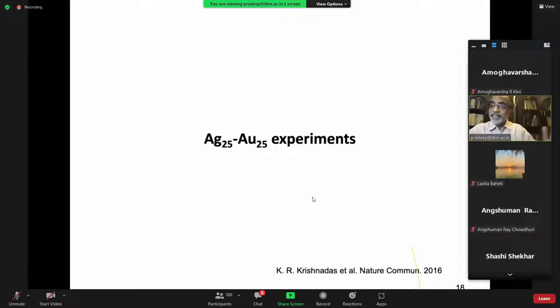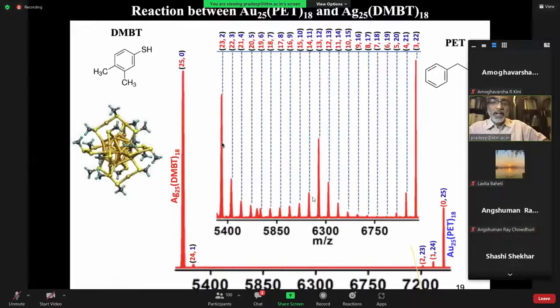Then immediately we started looking at another chemistry. How about this reaction instead of Ag44? And that was quite surprising. So if I take gold 25 and silver 25, take an equimolar mixture, this intensity is smaller than this intensity. This ionization is far more preferred.